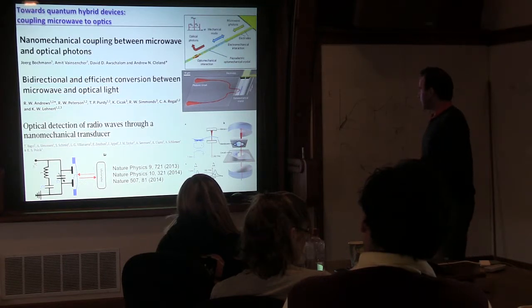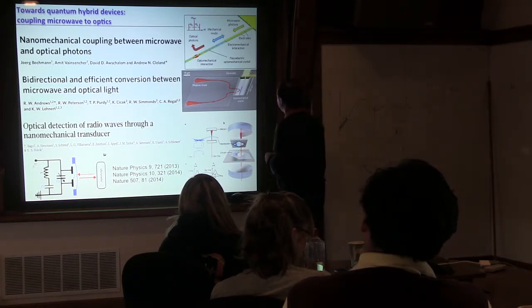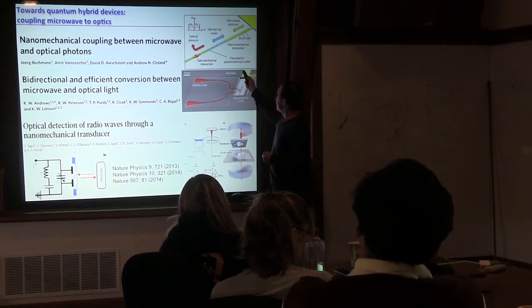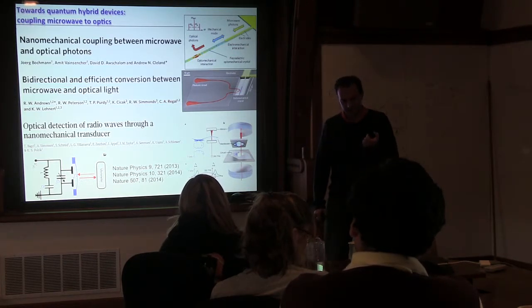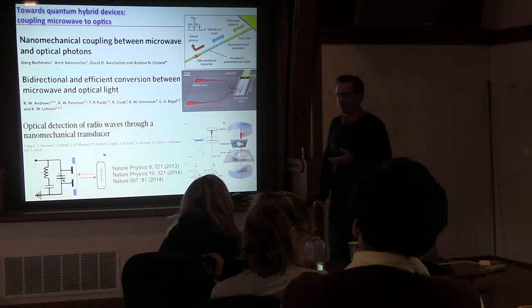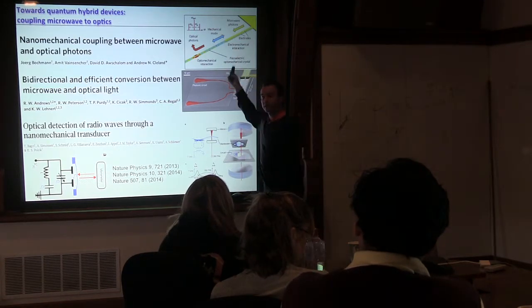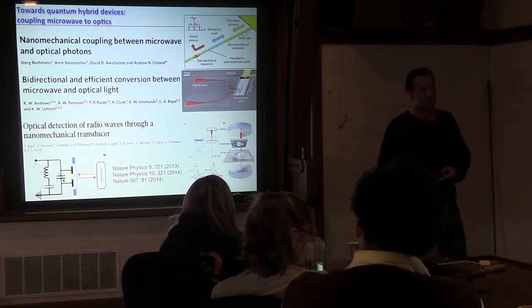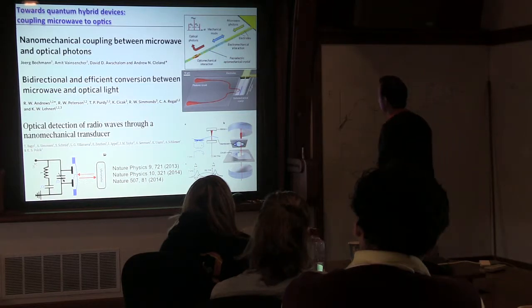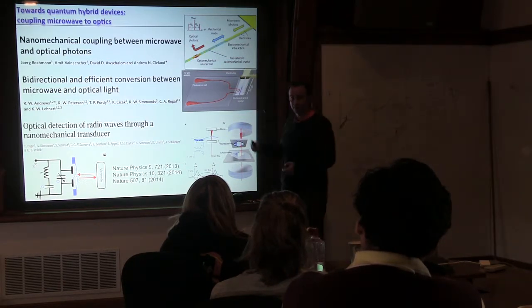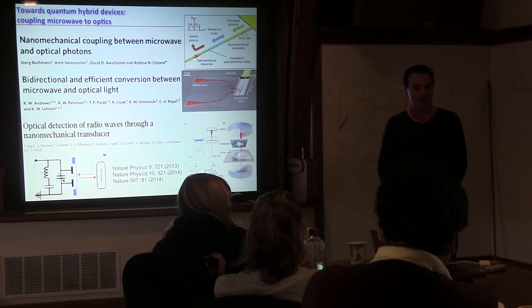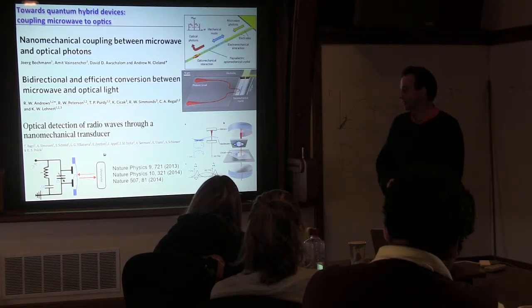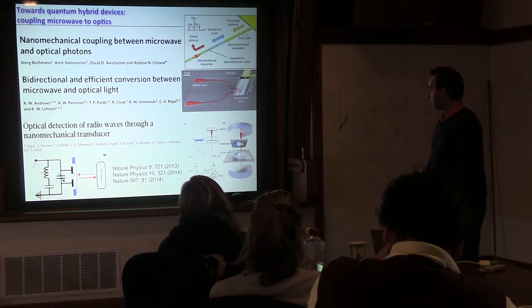So the challenges right now are essentially that it's extremely hard to have piezoelectric materials operating with low absorption, low losses in the optical domain. So what people have started out with here is aluminum nitride, for example, engineered that. They have relatively large absorption. Also a problem is, even if you have low absorption in the beginning, you want to operate that at 20 millikelvin. If you have a solid state system operating at 20 millikelvin, you send light in, optical photons, absorption is really a killer there. So it's still not really clear, I think, right now, how to overcome that.